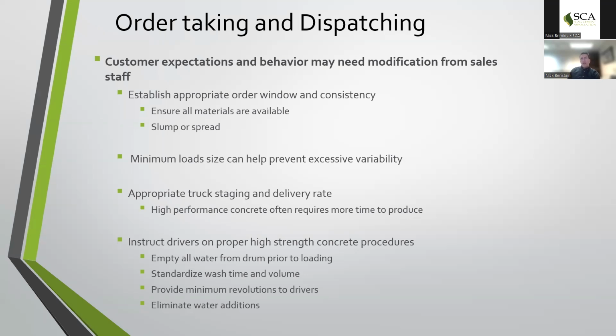Another good thing, if you are walking the line between slump and spread: after an 8-inch slump, the difference between an inch can be pretty dramatic on a job site. So potentially shifting over to a spread designation, because an 8-inch slump can be an 18 to a 21-inch spread. So if a customer has a very good idea of what they want, potentially switching them to that sort of ordering system can really help.